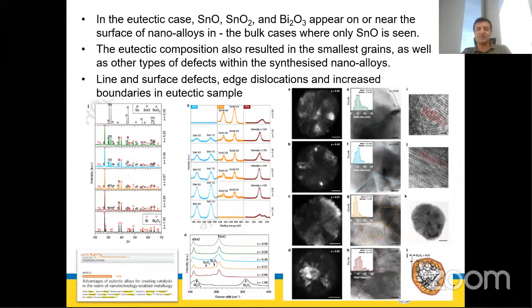for the catalytic properties. We sonicated them and we characterized the properties of this material. When you sonicate them, it's in the liquid on the surface, you produce tin oxide, tin dioxide, and bismuth oxide. And very interestingly, if you don't sonicate them, you only produce tin oxide. So it changes the thermodynamic of the surface. When you sonicate them at the eutectic system, you get lots of defects, edge dislocations, and boundaries. You don't have this much concentration of this kind of defects while you're using non-eutectic mixes.